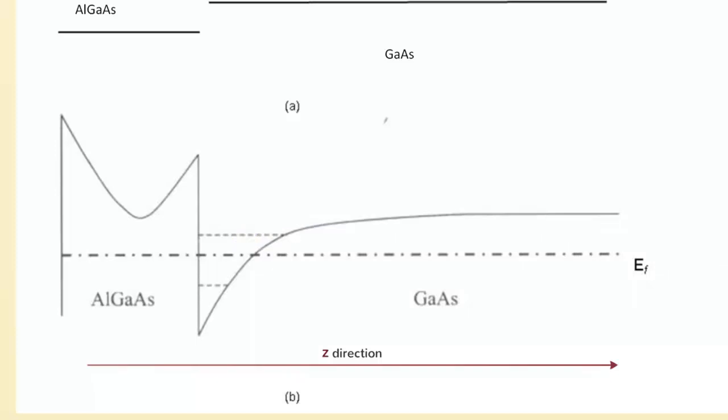The presence of this conduction band edge discontinuity forms a notch in the conduction band, as you can see, of the narrow gap material. And the electrons within this region of the semiconductor are confined in a triangular well-like potential. Within this potential well, spatial quantization occurs, and spatial quantization produces discrete energy bands called subbands in the potential well. The direction of quantization is perpendicular to the heterointerface, and the energy along this direction is quantized. However, in the directions parallel to the interface, effectively x and y, no spatial quantization effects occur, since the motion of the electrons is not restricted by the band bending.